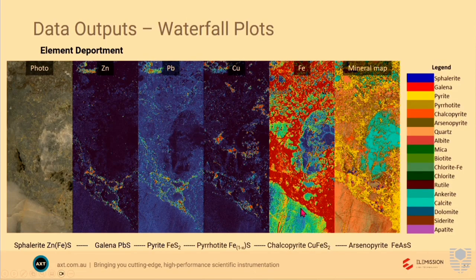So if you look at this one, it's quite active with iron. But then if you start looking at the element deportment, so the whole mineralogy, you can really see where the sphalerite is. So that's the zinc mineral. In this particular case, the sphalerite had a bit of iron. Galena, lead sulfide, no iron, but you've got pyrite versus pyrrhotite. So those chemical formulas are very, very similar.